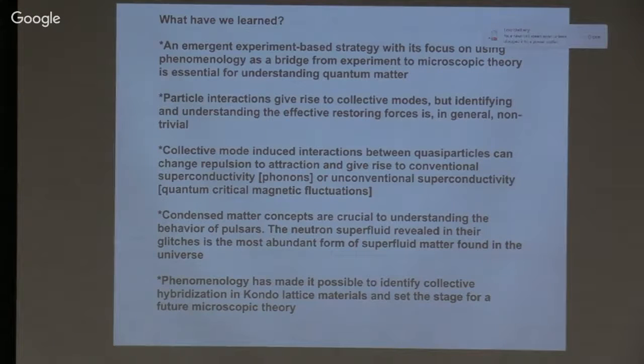So we have a strategy for dealing with emergent behavior in quantum matter. First, we learn that particle interactions can give rise to collective modes, but sorting out the effective restoring forces is non-trivial and has yet to be done really microscopically. But the phenomenological approach we developed in Urbana seems to work really well. And was predictive. We predicted the behavior of the modes seen in the helium-3 before they were seen experimentally. We also learned that collective mode-induced interactions can change repulsion to attraction and give rise to both conventional superconductivity and unconventional superconductivity from the quantum critical magnetic fluctuation.